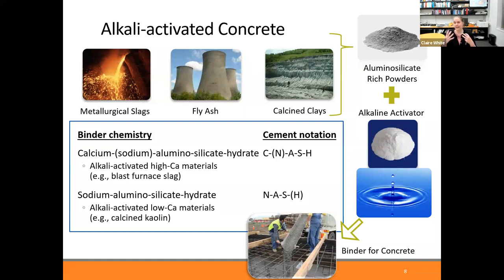And so we want to understand how those phases impact long-term performance of this material. In terms of the gels that give the concrete strength here, there's once again this CNASH gel that exists, but that's only when you have a lot of calcium in your system. If you don't have calcium in your system, say if you've got alkali-activated calcined clays, which are actually low in calcium, you end up with a different gel, which we call NASH.